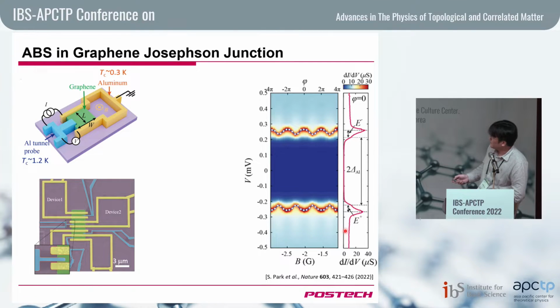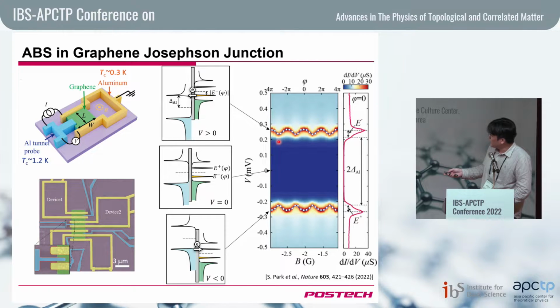So we made this kind of device by putting two ohmic contact superconductors onto graphene to make a Josephson junction and make a ring, and apply a magnetic field to control the phase difference between these two superconductors, okay? And then we put a side tunneling contact, using another aluminum electrode, onto the side of the graphene, and then we measure the dI/dV curve of this tunneling probe as a function of external magnetic field, which tunes the phase difference. So you see the periodic oscillation of this dI/dV peak, each peak coming from the lower and upper Andreev bound state that I just showed you. Okay, this is good. The peak looks sharp enough for us to do something more interesting.